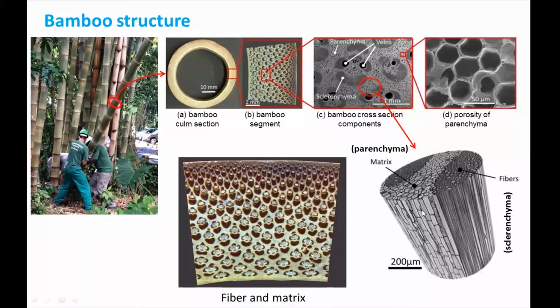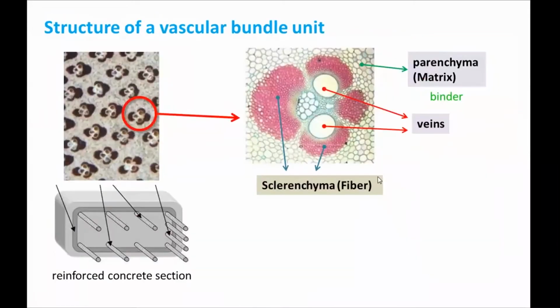And indeed, the matrix works only as a binder for the fibers, exactly the same as the reinforced concrete that we can see here. For reinforced concrete, we can see the bars and the matrix, which is concrete. Exactly the same happens in the cross section of bamboo. The bars are the fibers, the sclerenchyma, and the parenchyma or matrix is the binder. And you can see veins here also, the hollow tubes for feeding the bamboo.